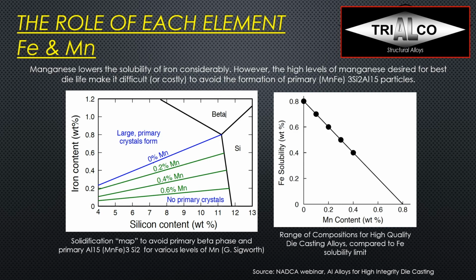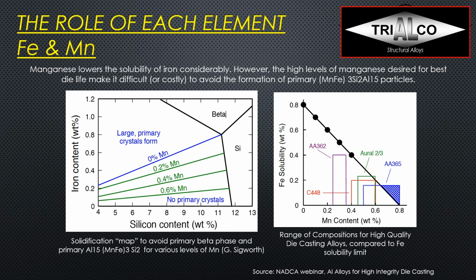So if we plot that iron solubility against the manganese content, we can see here on the right side, and pretty much all the typical structural die casting alloys are just below this curve. So we want to be relatively close to it. We want to have enough manganese to beat die soldering and not get into die sticking issues. We do not want to get much beyond it to get sludge formation, and we want to avoid the formation of these large primary crystals.